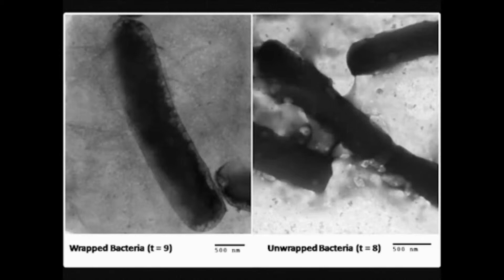Vikas Berry and his team created a solution by applying graphene, which protects the bacteria from losing water and images the cell at its natural size. The protective carbon cloaks are wrapped around the bacteria by either placing a sheet of graphene on top or by wrapping the bacteria with graphene solution. In both cases, the graphene sheets were functionalized with a protein to enhance binding with the bacterial cell wall. Under the high vacuum of an electron microscope, the wrapped bacteria did not change in size for 30 minutes, giving scientists enough time to observe them. Also, graphene's transparency to electrons enabled clean imaging of the cells.